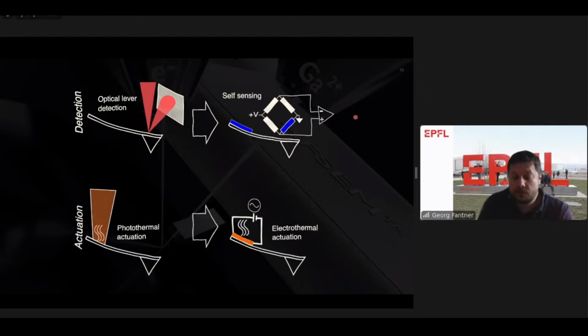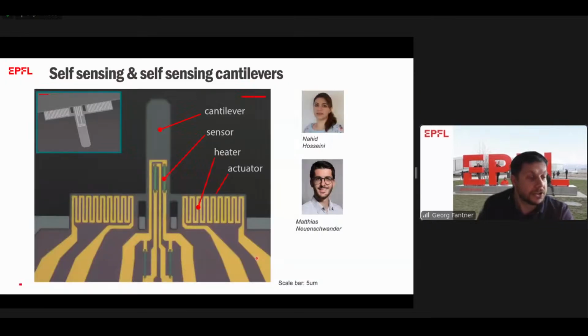In the same way as we have to replace the optical lever deflection, we also have to replace the optical actuation, so the photothermal actuation. We're doing that by building little microheaters into the cantilever so that we can electrically heat the cantilever and create the actuation that we need for the high speed of resonance tapping. And here I'm just showing a very brief view of one of those cantilevers that are microfabricated at EPFL. It's a completely new microfabrication process, which is a combination of traditional silicon nitride and the polymer processes that I introduced earlier in the talk. So these are not just intelligent, but also very fast cantilevers.